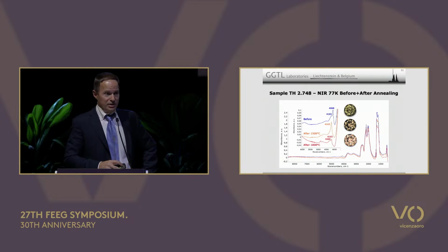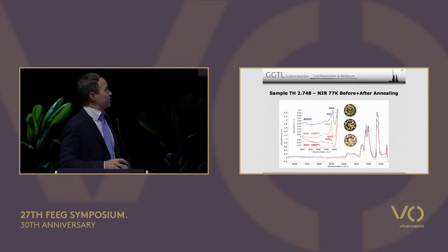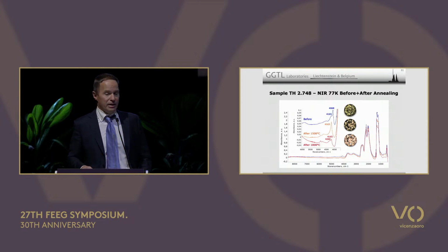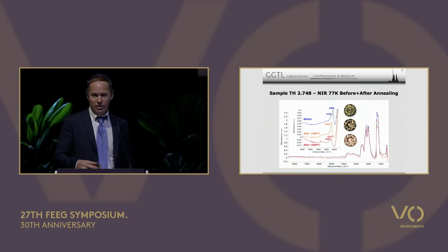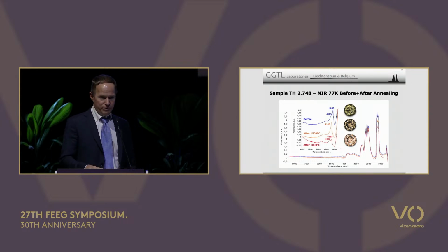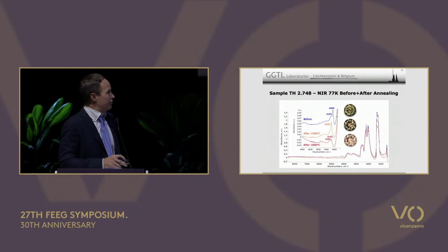Now here starts the interesting part. What happens upon annealing? So this stone was annealed at 1500 degrees Celsius and at 1800. And I had annealed it also at lower, so it was annealed at about 1000 first to see if something happened. We went steadily up to see at what temperature actually something dramatic happened, and it was around 1500. Some of the stones started to slightly change around 1150, but 1500 was quite dramatic.